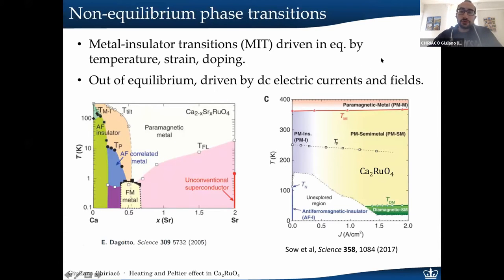Metal-insulator transitions have been very studied in recent years. In equilibrium, they can be driven by many tuning parameters, like, for example, temperature, strain, doping, and many more. You can see just an example in this phase diagram here, which is for calcium ruthenate doped with strontium. Depending on temperature or doping, you can have many different phases in this material. This is just in equilibrium.